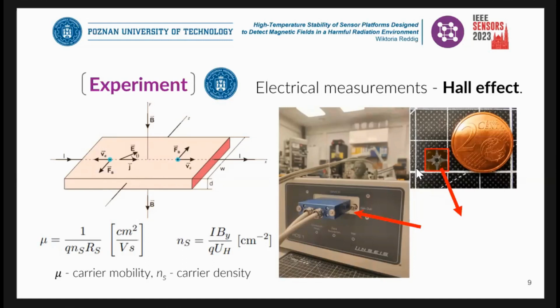There was the picture with the holder that holds the sample, and so we can make the 4-point measurement of the samples and measure the Hall voltage and sheet resistance, from which we can calculate the carrier mobility and carrier density. The holder that you cannot see here is a ceramic one, which allows us for precise temperature changes and to modify the temperature of the sensor.